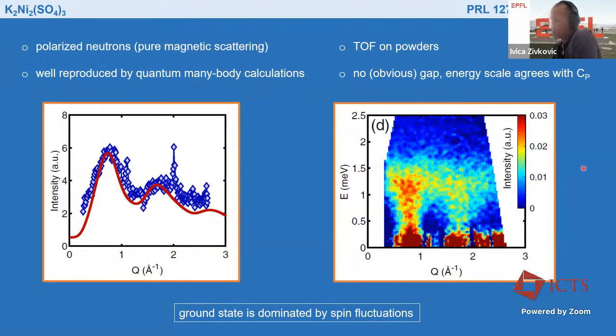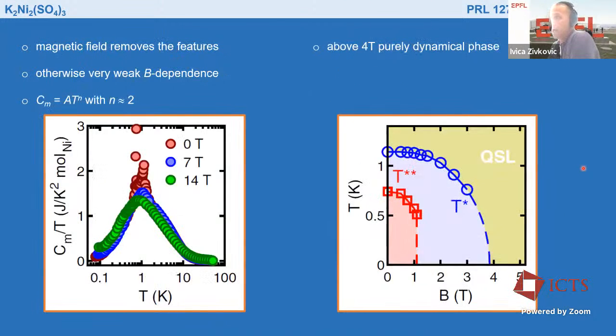So in conclusion, although there are these two small features appearing at around 1 Kelvin, we believe that these features have quite minor influence on the dominant behavior of this material, which is dominated by spin fluctuations. If you apply a magnetic field, we did it for specific heat, you can see that these features disappear, but the overall shape is basically unchanged.